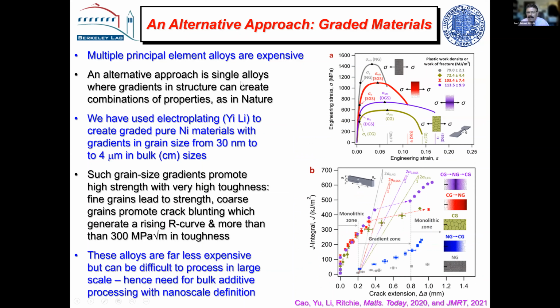The fine grain structure has very high strength. The coarse grain structure has very, very good ductility. And if you make these gradients, you can combine the best of both worlds. And depending on which way the gradient is going, you can generate very, very high properties. These are toughnesses here in just pure nickel with a variety of different gradients from coarse to fine to coarse, from coarse to fine, fine to coarse. And we're getting toughnesses up here of about 250 megapascal root meters in nickel. And you've got a strength level here in the gradient ones of well over a gigapascal.